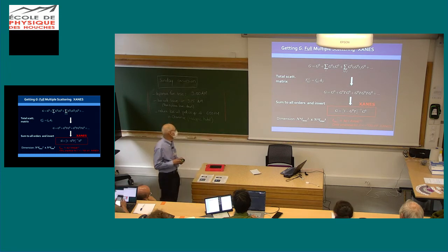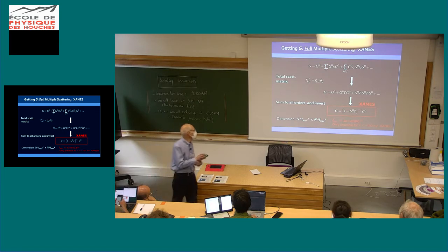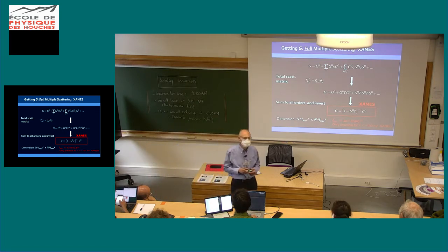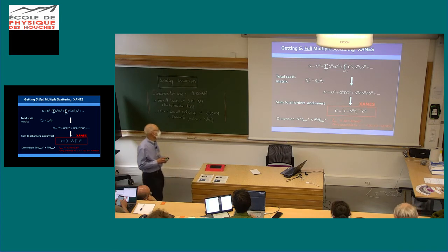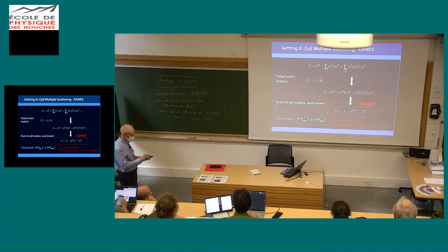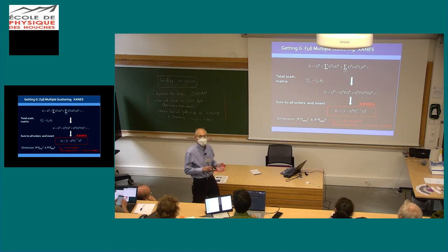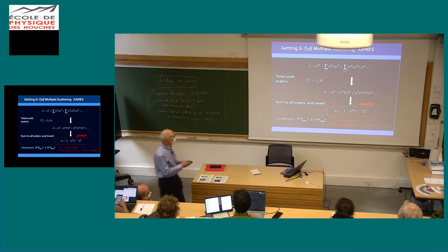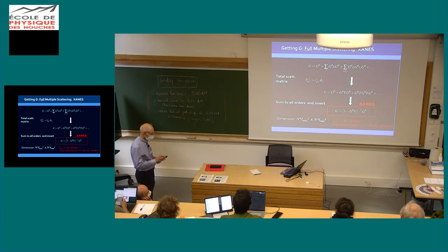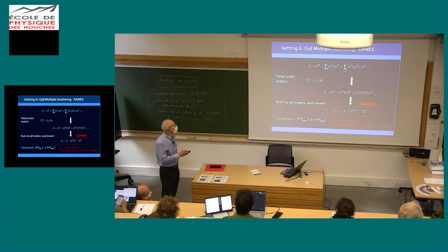You quickly run into computational difficulties. And so it is only practical to do this matrix inverse at relatively low energies, no matter what size computer you have. I don't think you can really get it much higher than a few hundred eV when you're lucky. And if you have a lot of atoms in your problem, like you're doing a surface or something with some impurities, anyway, you see how it grows. So you have to pay attention to the matrix to see what's possible or not.